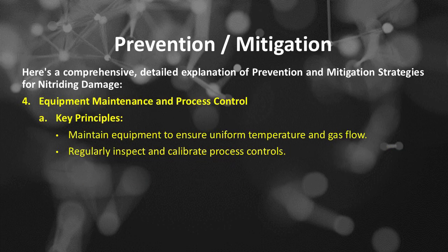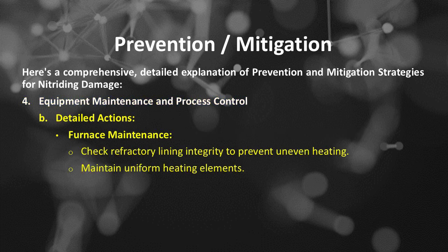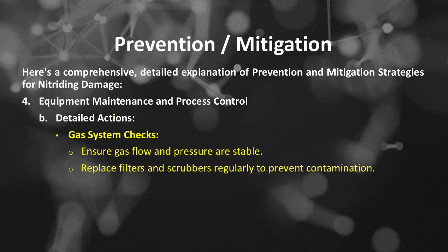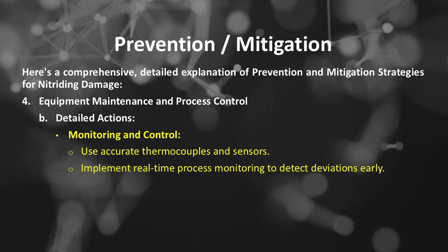Number 4 of prevention and mitigation strategies for nitriding damage is equipment maintenance and process control. The key principles include maintaining equipment to ensure uniform temperature and gas flow, and regularly inspecting and calibrating process controls. Detailed actions in furnace maintenance: check refractory lining integrity to prevent uneven heating, and maintain uniform heating elements. Detailed actions in gas system checks: ensure gas flow and pressure are stable, and replace filters and scrubbers regularly to prevent contamination. Detailed actions in monitoring and control: use accurate thermocouples and sensors, and implement real-time process monitoring to detect deviations early.